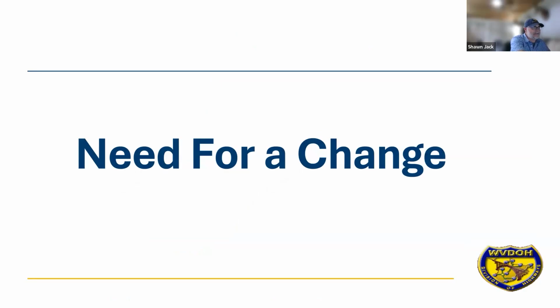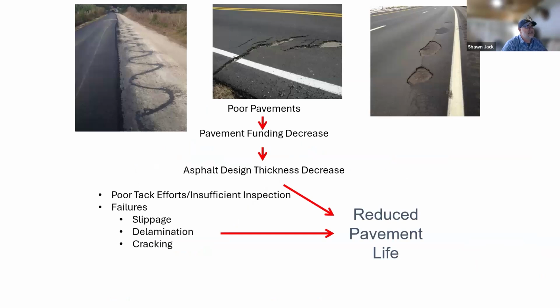Back around 2011 or 12, we identified the need for a change. We were seeing poor pavements, increasingly poor pavements. There was a decrease in funding availability. As a result, there was a decrease in the asphalt design thickness. We also took notice of, and I think Randy mentioned this, poor tack coat efforts and insufficient inspection, which is on us. But I guess we looked at all the ways we might be able to address that, and to help fight this losing battle.